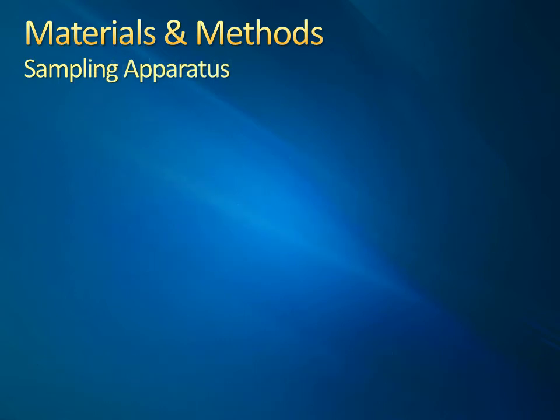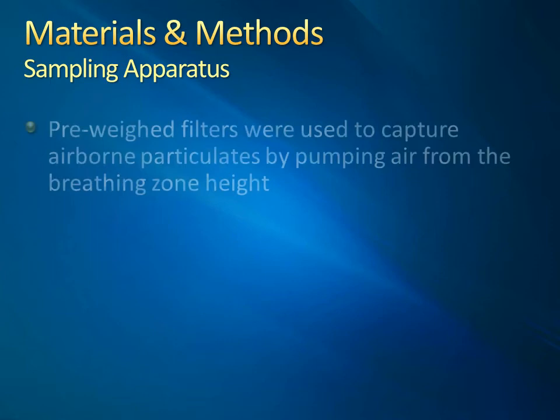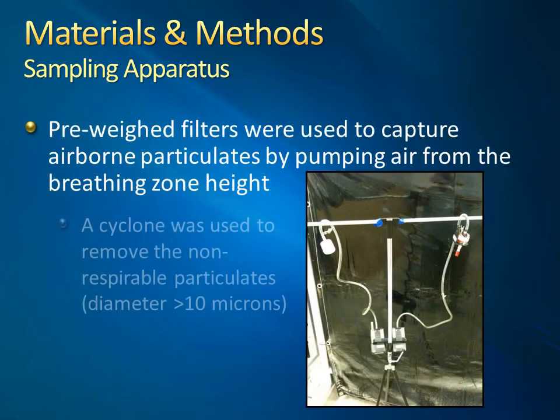For sampling, a pre-weighed polyvinyl chloride or mixed cellulose filter, depending on the method, was placed into a filter holder. For the silica sampling, a cyclone was attached to the filter cassette. The cyclone was required to remove any silica that was larger than the respirable limit of 10 microns.